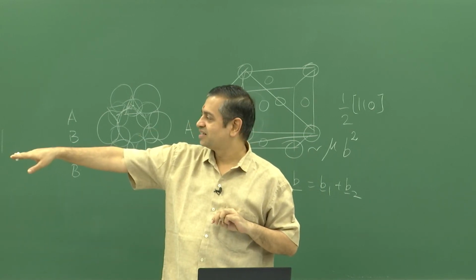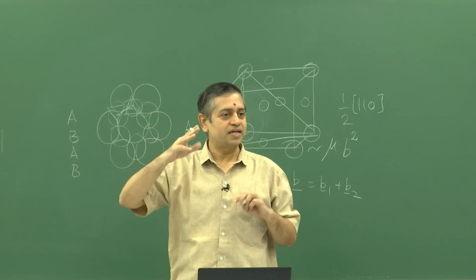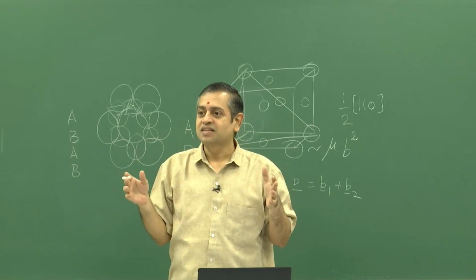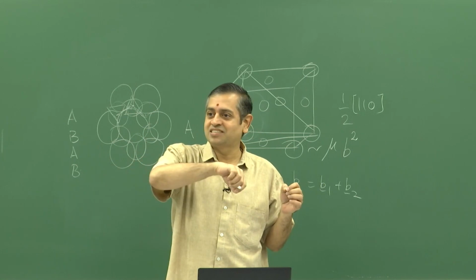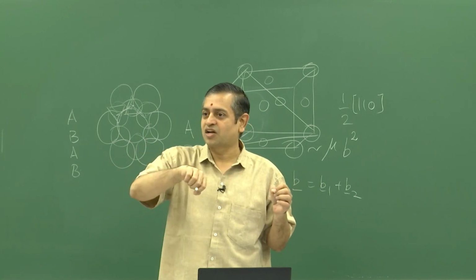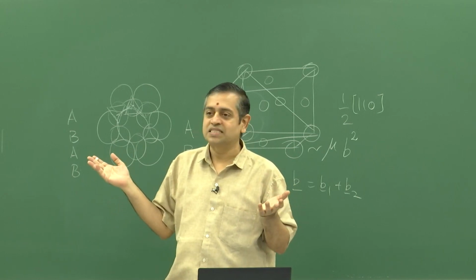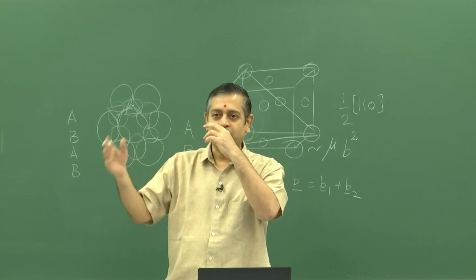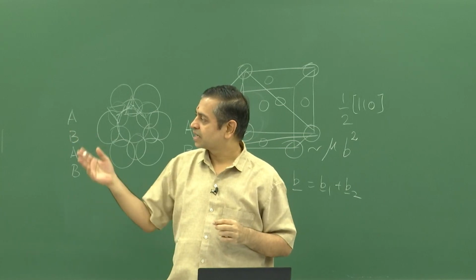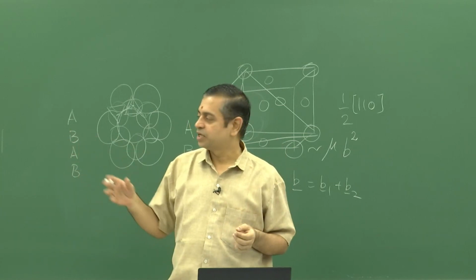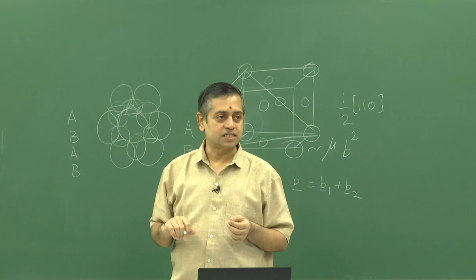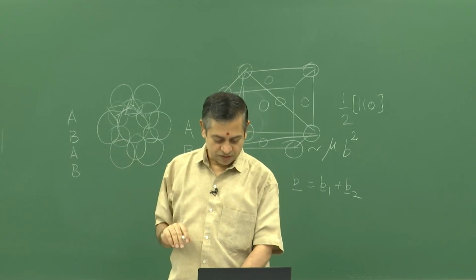300 Kelvin is where we are interested, and because it is a single phase in which you can methodically change the stacking fault energy with alloying, it becomes a nice system to study. Everything else more or less remains the same, only the lattice parameter, Burgers vector, and the stacking fault energy change predominantly, and then you can study the system. So, that is why this is of interest.